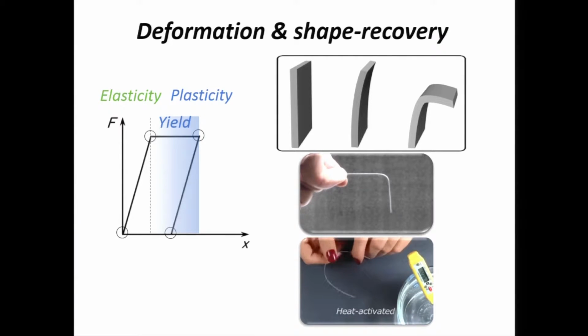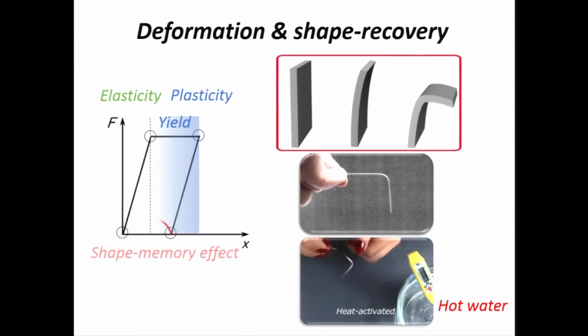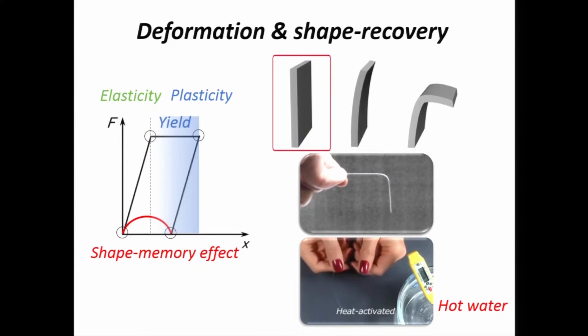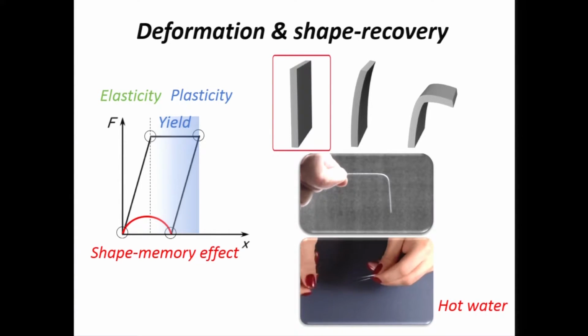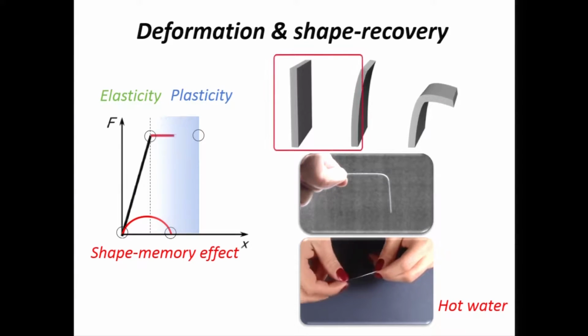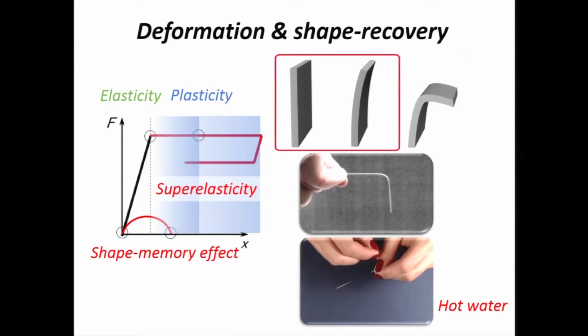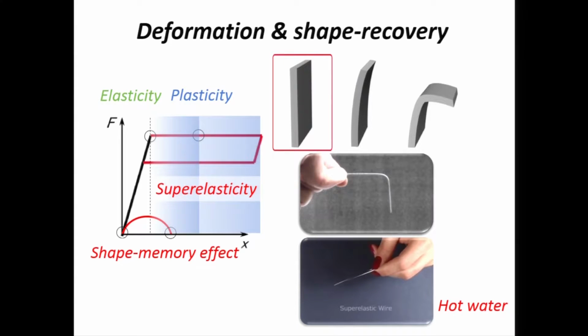So this is a titanium nickel shape memory alloy. Now the same plastic deformation occurs, and we warm this material up to more than the transition temperature. In the higher temperature region, this material has a superelastic phase, a crystal phase capable of superelasticity. And in the superelastic region, the plastic deformation range is very wide. And surprisingly, very strangely, it spontaneously recovers with constant force.